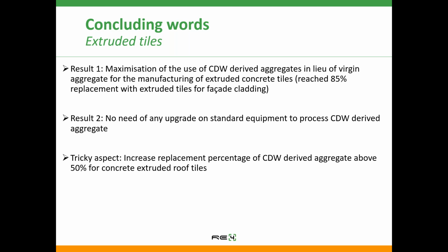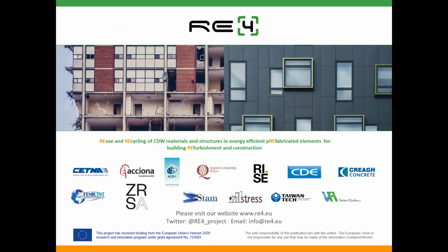Second result, very important, good news for those who already have a plant on site, is that there isn't any need of any upgrade on standard equipment to process CDW-derived aggregates. And as told before, the most tricky aspect was that concrete roof tiles imposed a quite low replacement rate, which was anyway within the minimum target that was one of the main goals within the project at the beginning in 2016.